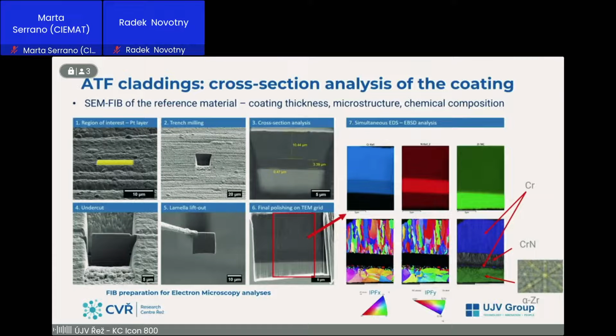So going to some results from ATF claddings, where we can do the cross-section analysis using focused ion beam. Here is the workflow to prepare the TEM lamella, which we do within the SEM chamber, and then we do the chemical analysis and electron backscatter diffraction of chromium and chromium nitride coated specimens.